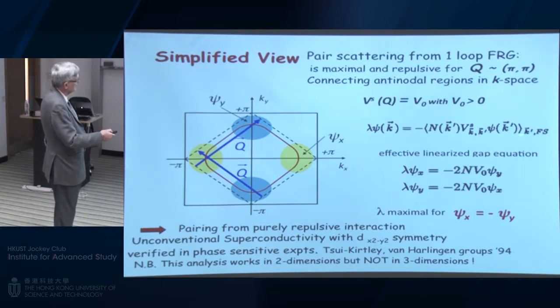So if we simply take this wave function here and map it around these areas, then we can get a nice solution if we have the sign here opposite to the sign here, because then if we just concentrate in the simplified view on these regions, we have a psi x coupled to minus psi y, and a psi y coupled to minus psi x. So we get a good solution with a high eigenvalue where these two, x and y, are opposite. So this says that this superconductivity should be D-wave.